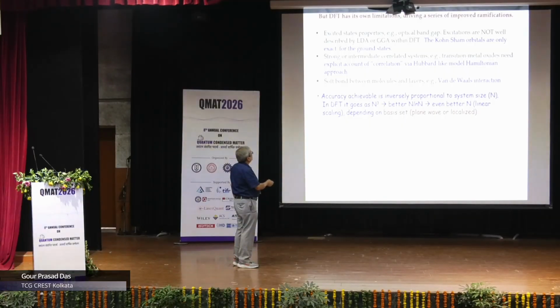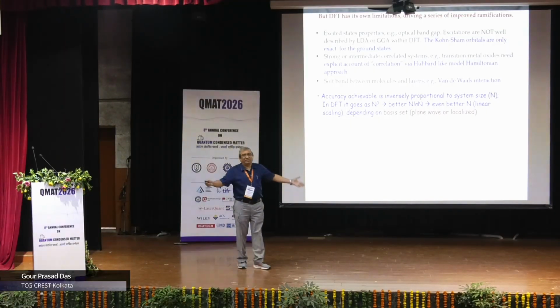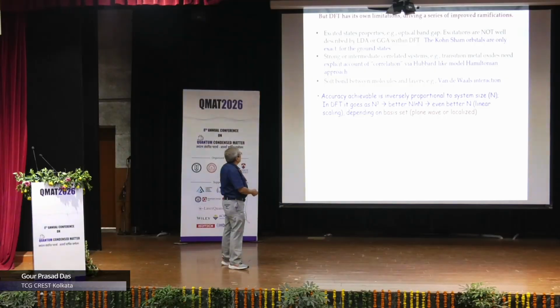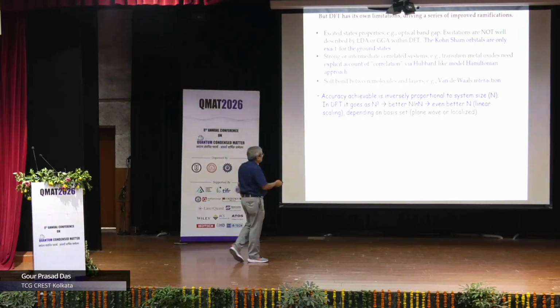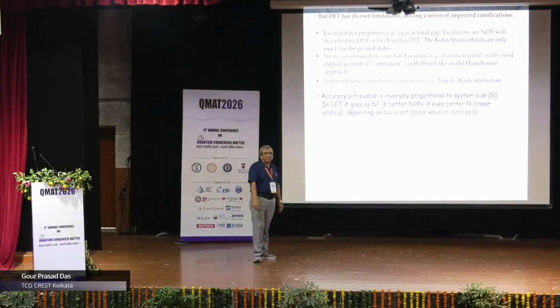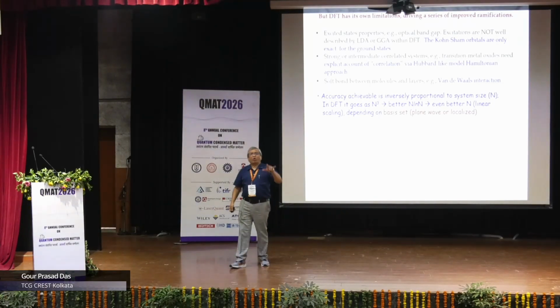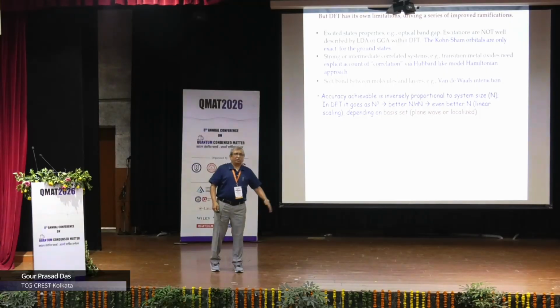Now in DFT, it goes as n cube. Sometimes it is better, it is n log n, or even better, which is linear scaling, proportional to n. N is the number of atoms in the supercell or the unit cell. But the accuracy which is achievable and the scaling depend on the basis set, whether you are using a plane wave basis set or a localized basis set or an augmented basis set, and so on and so forth, okay?